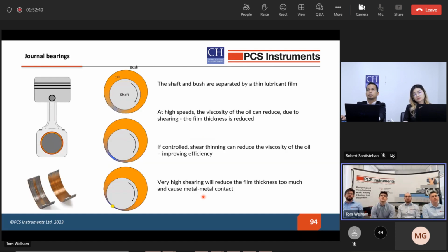So looking now at the case of a crankshaft journal bearing, we can illustrate some of the effects of shear thinning. Typically the metal surfaces are separated by a thin oil film, but at high speeds this shear thinning effect can occur, which potentially can improve efficiency via a drop in viscosity. So you're wasting less energy shearing the viscous fluid, but if the viscosity drops too low, metal to metal contact can occur, and that can cause wear and energy losses. So there's actually an optimum level of shear thinning.